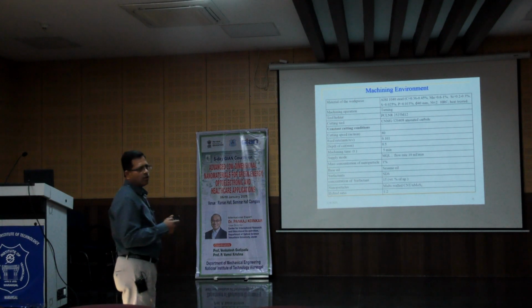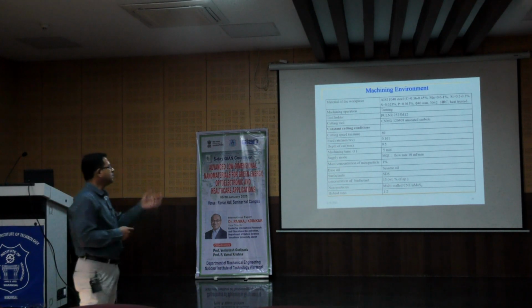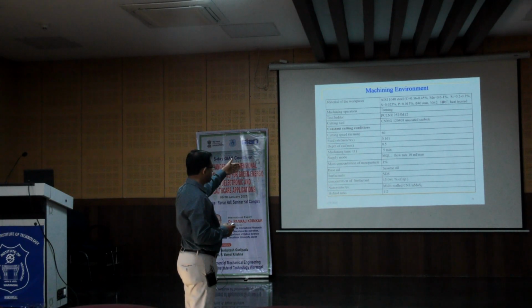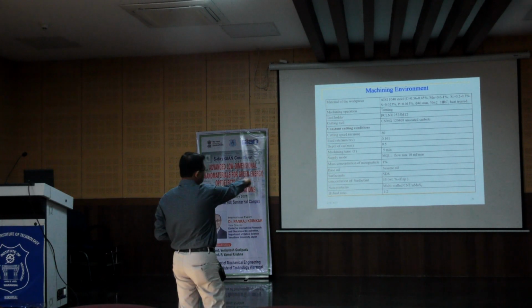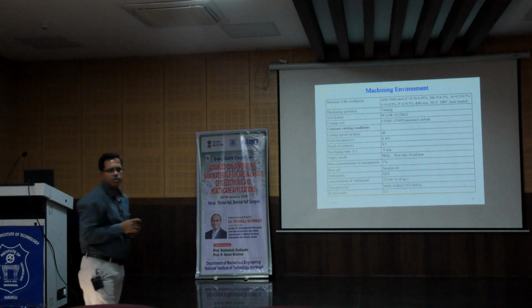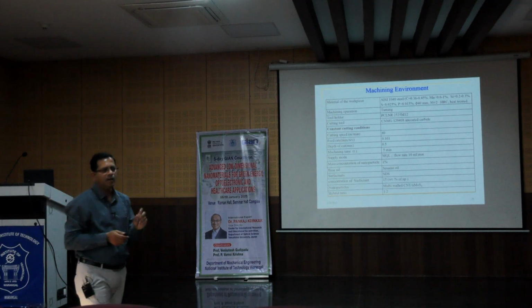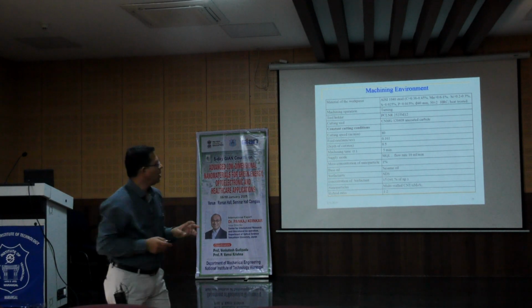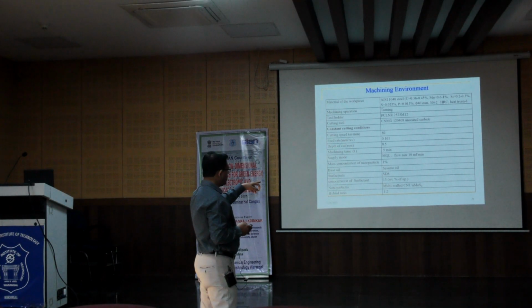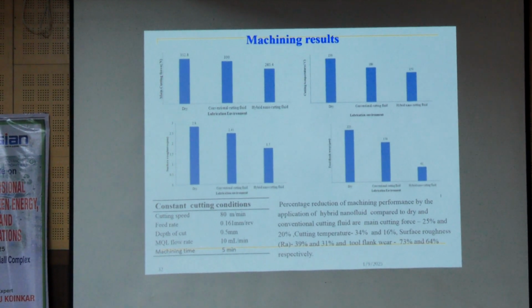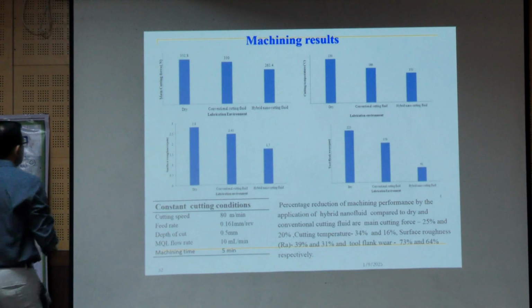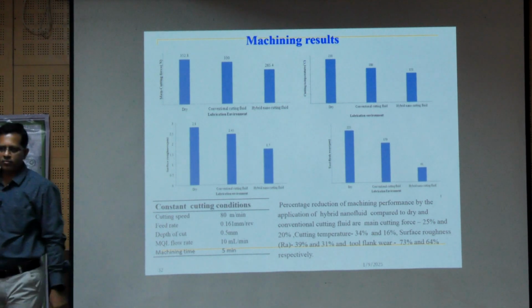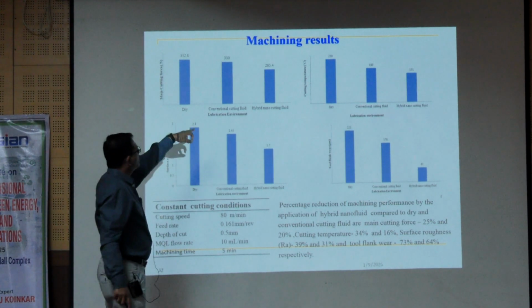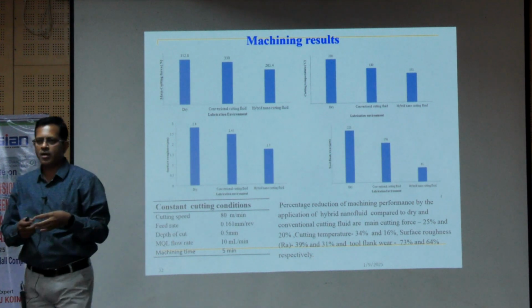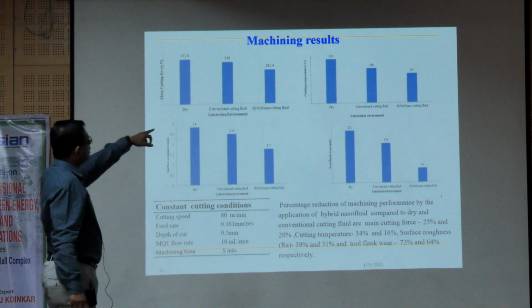So we took a normal lathe machine and went for a turning operation. These are the conditions: the cutting speed, feed rate, depth of cut, etc. And we are using MQL at a flow rate of 10 ml per minute. The ratio of CNT to MoS2 is 1:2, that means if we take 1 gram of CNT, 2 grams of MoS2 is taken. Then, for cutting force, here if you see, this is dry machining, that means without using a cutting fluid, this is conventional cutting fluid, whatever I told you, a mixture of water, oil and surfactant, and this is the hybrid nano cutting fluid.